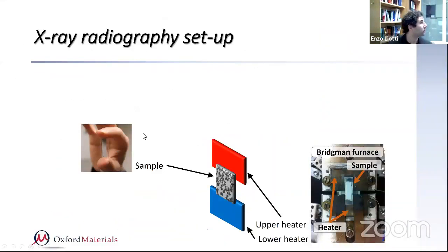So how does a normal radiography setup work? Well, normally you've got a sample, for which we use a very thin foil encapsulated in a container. In this case, it is a quartz cell, and then we put it in a furnace, which is a small Bridgman furnace. A Bridgman furnace is a furnace that has two chambers, and they can be controlled independently. In this case, you see a heater on the top and a heater on the bottom here. Because they can be controlled independently, we can impose an isothermal condition, or we can impose a thermal gradient and then cool at a different cooling rate.